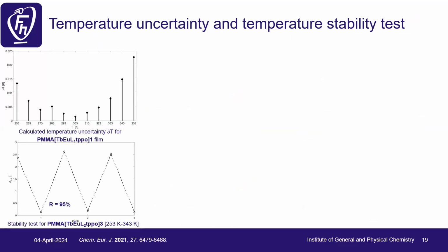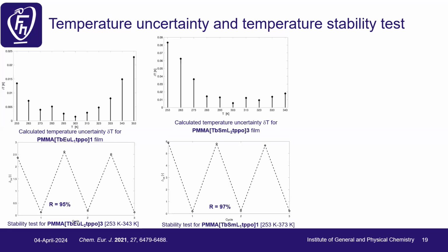At the end, here we can see the temperature uncertainty, which is quite low, almost 0.02 K, and repeatability of 3 cycles of 95%. So how we were doing this: we would heat up to the highest temperature, first cool it down, heat it up, measure once, then cool it down, heat it up again and again. But due to the setup constraints, we did only 3 cycles, not 4 or 5, because it takes a lot of time to heat up and cool. Similar was for the PMMA sample of terbium and samarium.